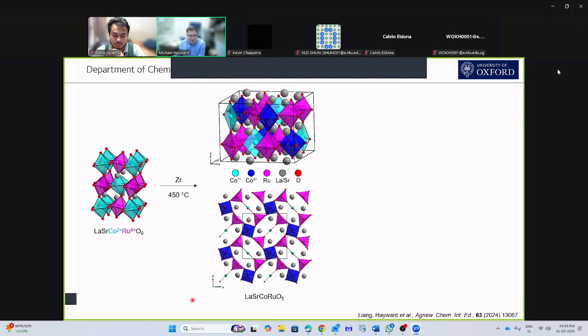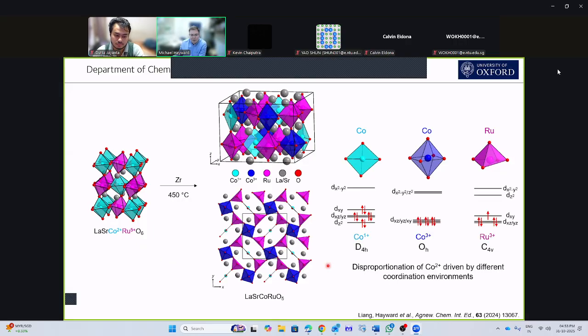And if we look at this structure, we see that our cobalt in blue comes in two different coordinations, a square planar version and an octahedral version, and then our ruthenium in purple sits in a 5-coordinate structure. And if we analyze this a bit more, we realize actually what we've done is we've got a cobalt 2 oxidation state on average, but actually this is disproportionated to cobalt 1 and cobalt 3, driven by the D8 square planar preference and the D6 low spin octahedral preference. So we have a rather unusual situation where we've disproportionated cobalt 2.